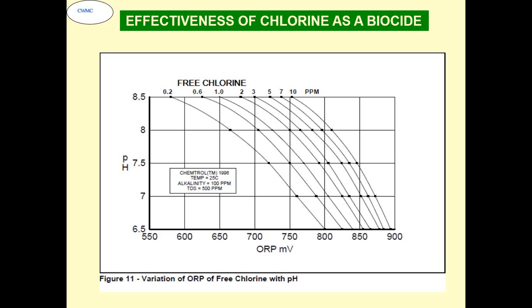Now in that case, even if you are maintaining 0.2 ppm free residual chlorine, and the system is effectively working, you will get more than 550 millivolt ORP. In very good conditions, you can get even up to 800 millivolt, but at least around 550 to 600 is a normal thing that you can expect in a good clean system.